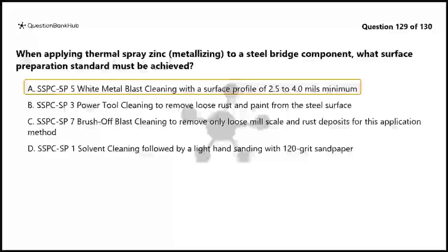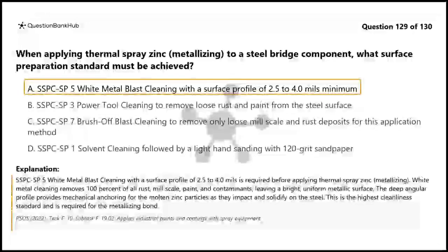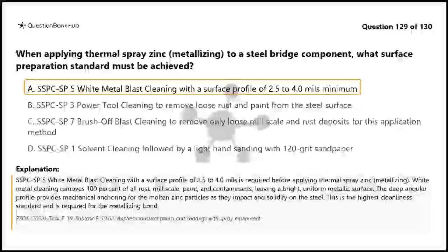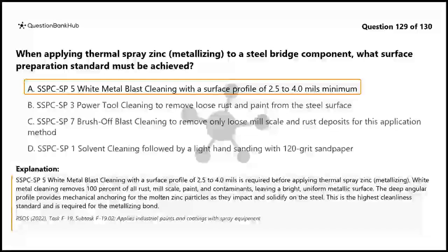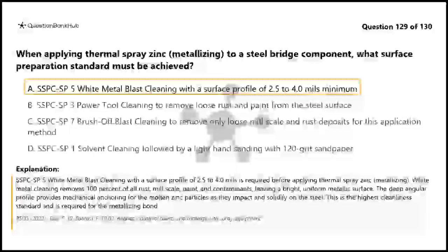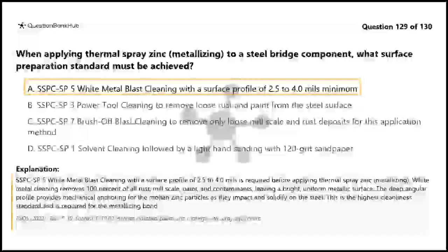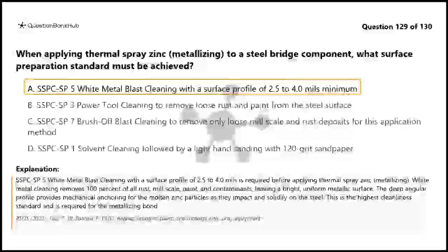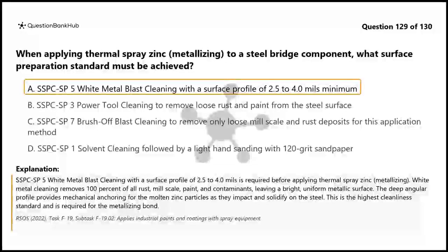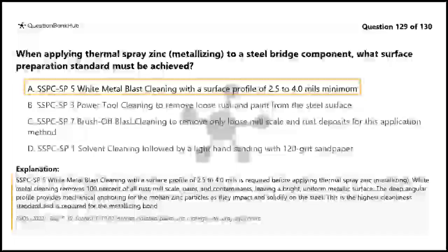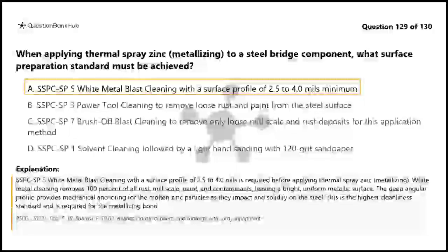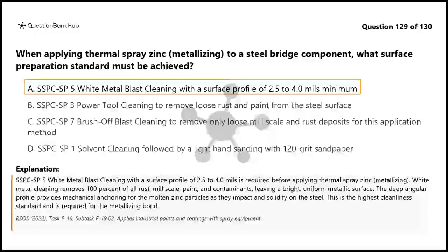The correct answer is A. SSPC-SP 5 white metal blast cleaning with a surface profile of 2.5 to 4.0 mils is required before applying thermal spray zinc, metallizing. White metal cleaning removes 100% of all rust, mill scale, paint, and contaminants, leaving a bright, uniform metallic surface. The deep angular profile provides mechanical anchoring for the molten zinc particles as they impact and solidify on the steel. This is the highest cleanliness standard and is required for the metallizing bond.